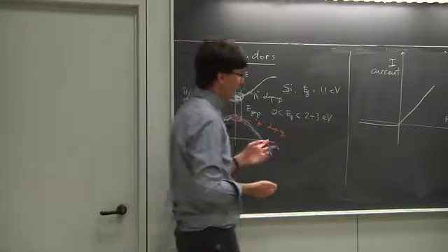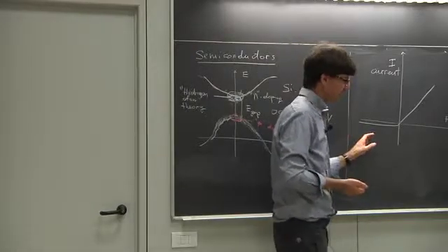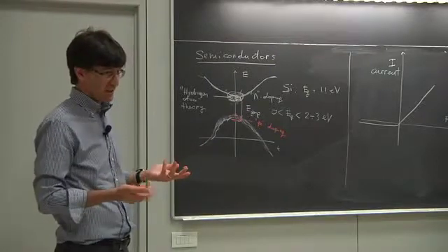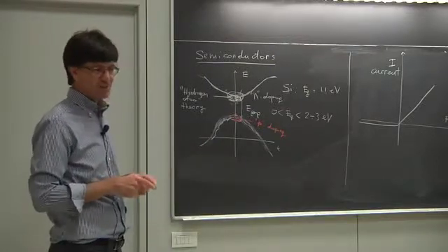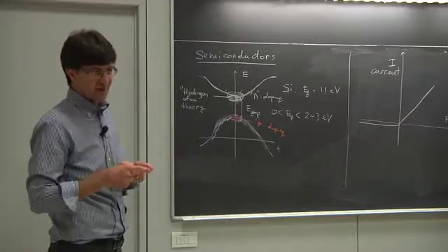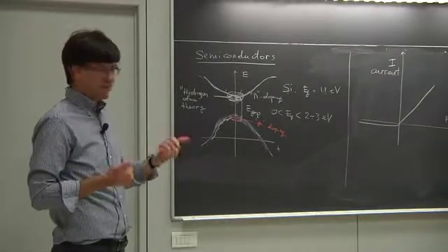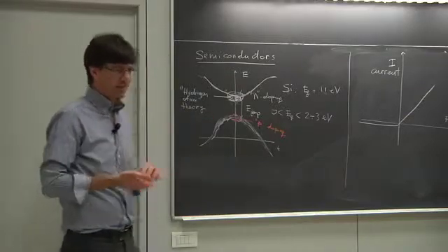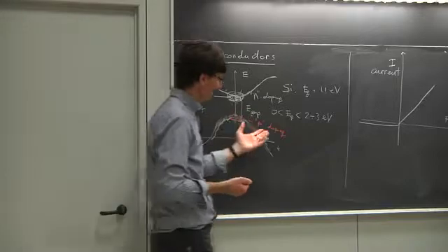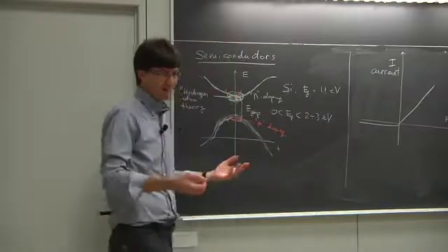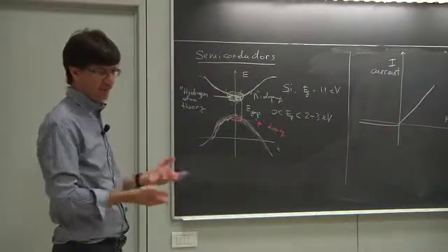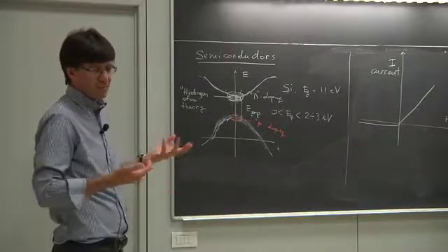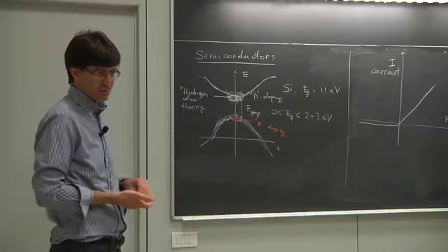Although, you have to be careful, because if you're talking about doping at the level of, say, 10 to the minus 8, 10 to the minus 7 concentration, if your particle has a size which is less than 10 to the 8 silicon atoms, for example, you don't have a single impurity there if your concentration of doping is too low. So doping is a concept that exists if the amount of atoms in your system is large enough that you can handle small concentrations of impurities. If the system is too small, what is the meaning of low concentration of impurities? It might be just 0.